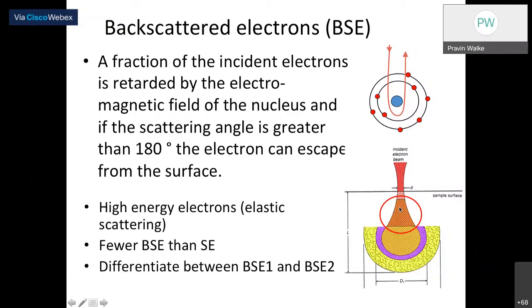These are nothing but the high energy electrons where we have elastic scattering. But if you compare secondary electrons and backscattered electrons, usually the backscattered electrons are fewer, right? And secondary electrons are more in the case of the SEM system. If someone wants to use backscattered electrons for certain applications, we'll talk about when we have to go for backscatter imaging and secondary electron imaging.